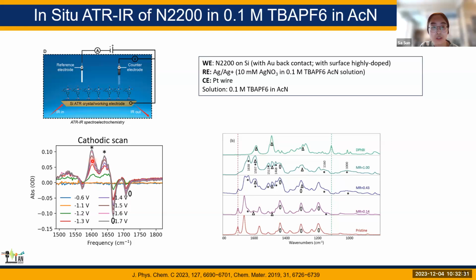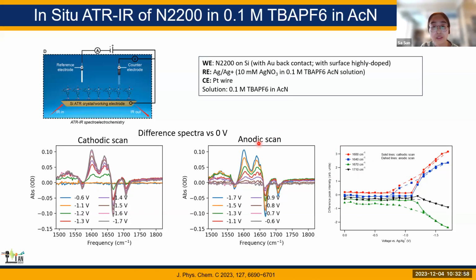We can see that there are 2 new features growing after the N2200 reduction. These 2 new features actually align with what they saw in IR spectra upon chemical doping. And these 2 species are actually the carbonyl stretching, which is vanishing, which is also aligned with what they observed. And the anodic scan actually shows the reversible trend.